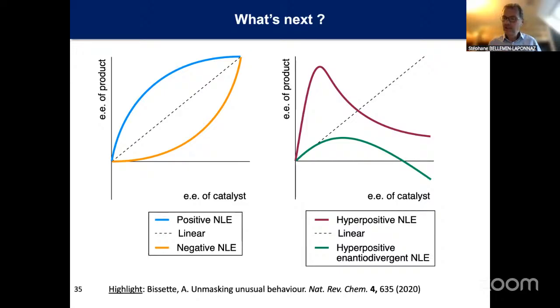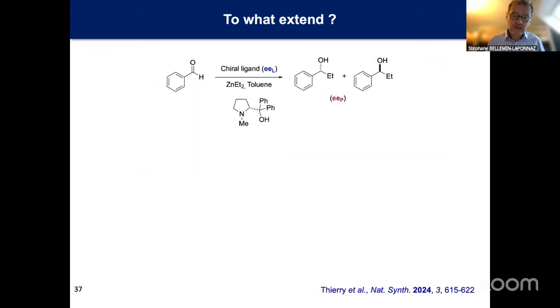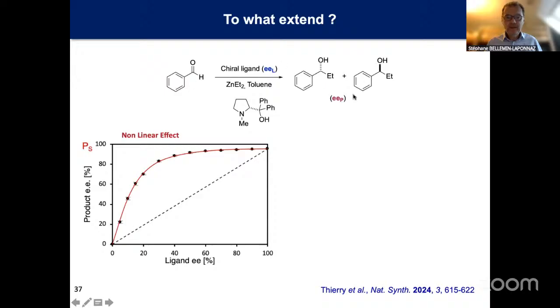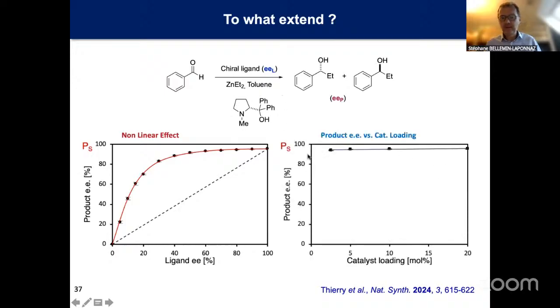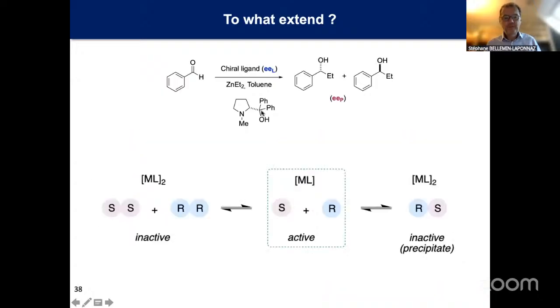Is this result only limited to a single reaction and a single ligand, or can we verify that in other asymmetric reactions? So to look at that, we first continued to look at reactions using ligands that are widely used in the literature, for example, the N-methyl diphenyl prolinol. We look at this reaction, for example, where the mechanism was not studied. If you look at the nonlinear effect on this reaction, we have a very nice positive nonlinear effect. And if you look at the impact of the catalyst loading, you have no impact of the catalyst loading.